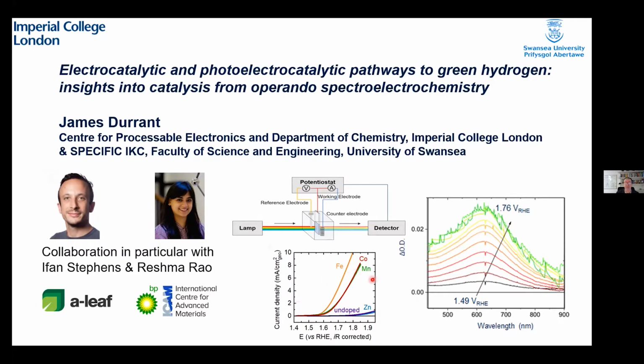And this is essentially the concept here, that if we simply take our electrocatalyst or indeed our photocatalyst film, when we apply a potential to it or we shine light on it, then we can measure performance not just by the current as a function of voltage or light intensity, but by the change in optical density of the film. And that ability to measure optical density, which gives us a direct handle on population, and maybe more interestingly, enables us to discriminate between different redox states, so different populations, gives us an additional handle on trying to understand how these wonderful materials work, or mysterious materials work.